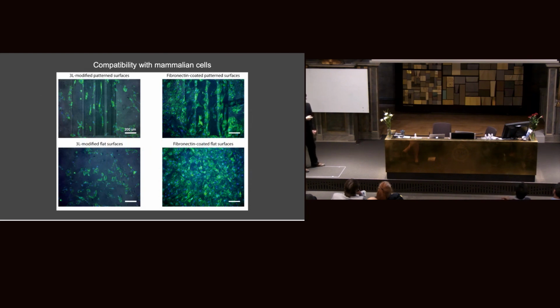To check the compatibility between our surface modification and human cells, we did cell culturing on the modified surface. We can see that the surface actually supports cell growth, although not as much as the fibronectin-coated surface, but it doesn't really do any harm to the cell. The fibronectin-coated pattern surface is usually used to promote cell adhesion and growth, making cells thrive. So this test shows that the surface is not toxic to human cells.